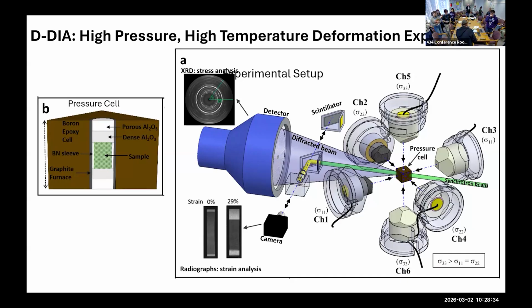Ultimately what you want to do is your sample will be at the center of this cell here. And then you'll have all these other components that go in around it. The purpose is we want to generate high pressure and temperature in our sample. So we have the sample at the center, and then we have these small parts that go in. These little black cylinders here, those are a furnace. So we can run a current through it and generate high temperature.